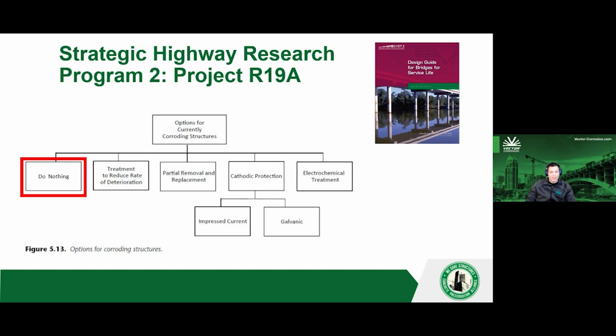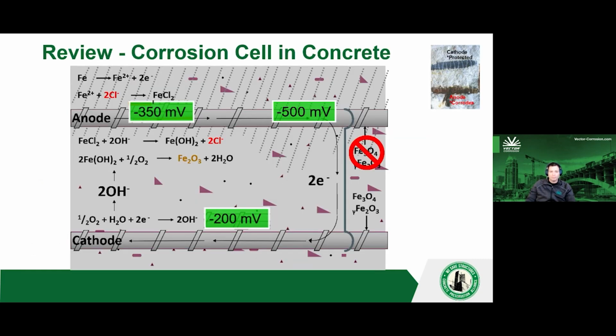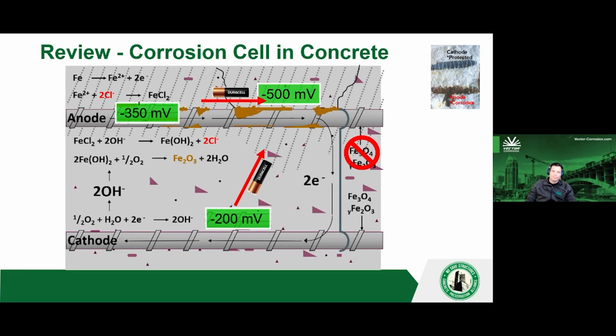And what does that look like in this case? If we just did nothing, the corrosion activity would just continue to go to this minus 500, the most negative area, most corrosive area. You're going to get corrosion, expansion, concrete cracking, and spalling. Okay, so usually this is the physical sign indicating to an owner, hey, I need to get this repair.